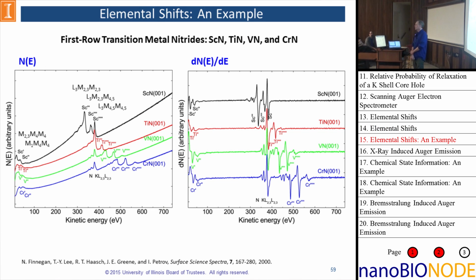And here I show two examples of Auger survey spectra for the first row transition metals, similar to the XPS data we showed earlier. The one thing you'll notice right away, though, is that the Auger transition is much more complicated in terms of number of lines and the energies they span as compared to the photoelectron lines. And that adds some complications to the spectroscopy in not only being able to identify elements, but also to be able to precisely do quantitative analysis. That's why it's also good to have an XPS system in the same lab as the Auger system.